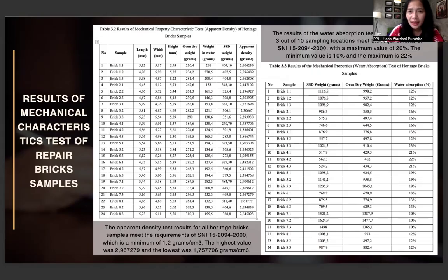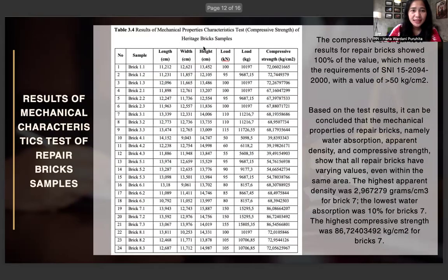And then at table 3.3, the result of mechanical properties about the water absorption test on heritage bricks: 3 out of 10 sampling locations meet the requirement of SNI with a maximum value of 20%. The minimum value is 10 and the maximum is 22%. And then the last test, the compressive strength test result for repair bricks, shows 100% of the values meet the requirement of SNI with a value of more than 50 kilograms per centimeter.